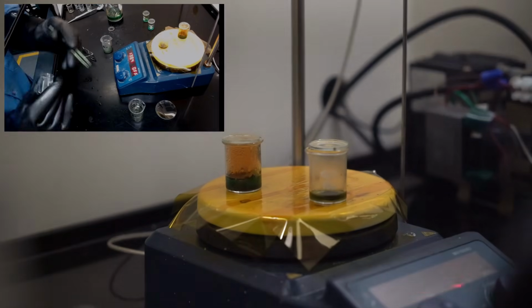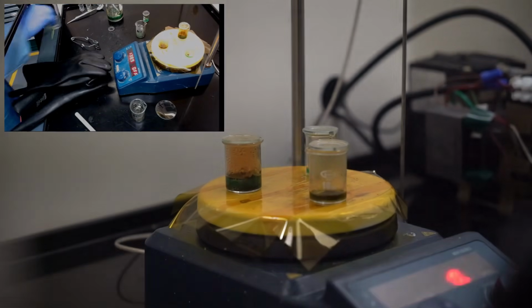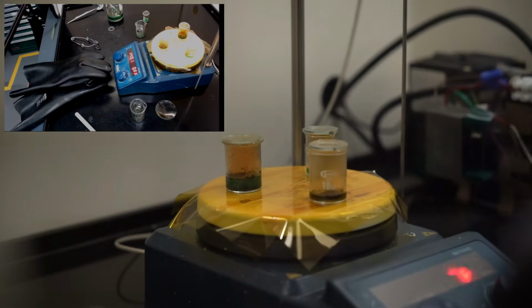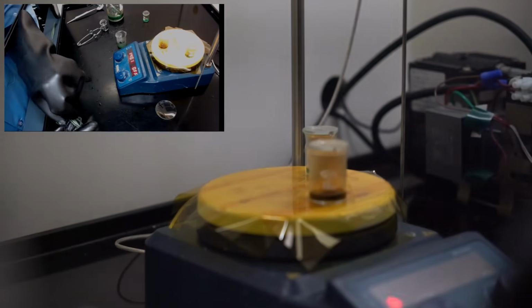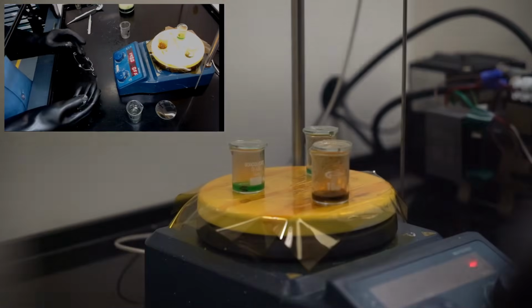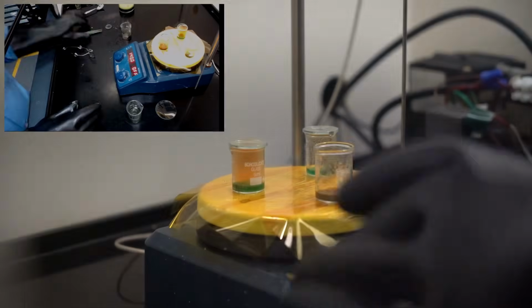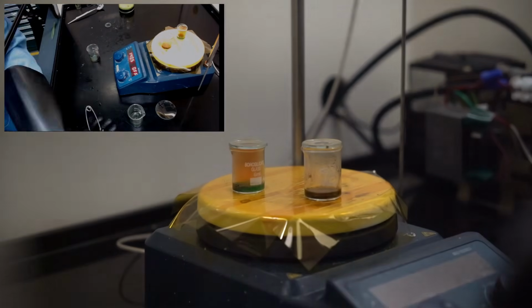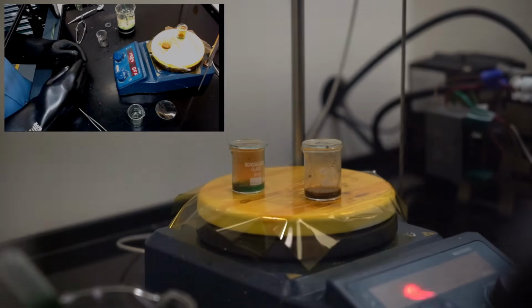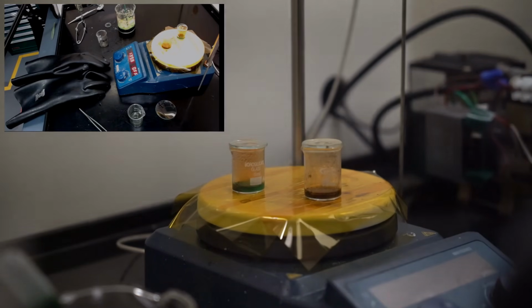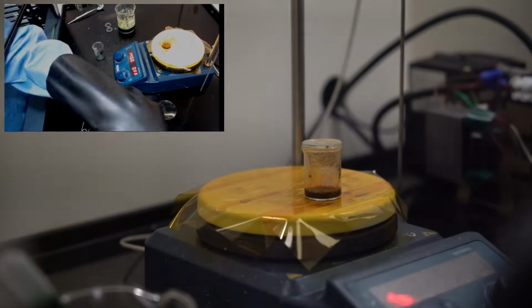And the second related reason is you'll notice that the waste is green. That's because there's a lot of dissolved copper salts in it, mostly copper nitrate in this case since we're decapping with nitric acid. And soluble copper salts have fairly high bioavailability and are quite toxic to wildlife. I don't want to be cleaning off my glassware and having copper salts getting down the drain. By neutralizing it first, most of the copper precipitates out as copper carbonate, which I can then filter off. Then I'll give all the glassware a quick wipe with a paper towel, hold on to those as essentially heavy metal waste, and whatever's left over can then be cleaned off with tap water, and I don't have to worry about polluting anything.